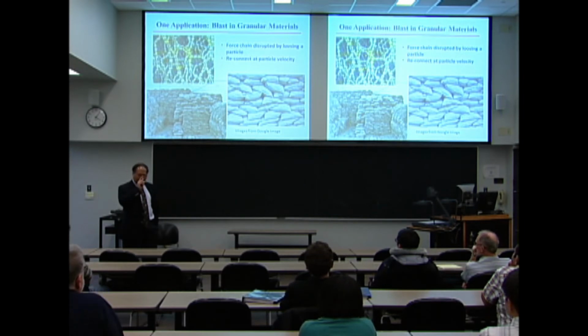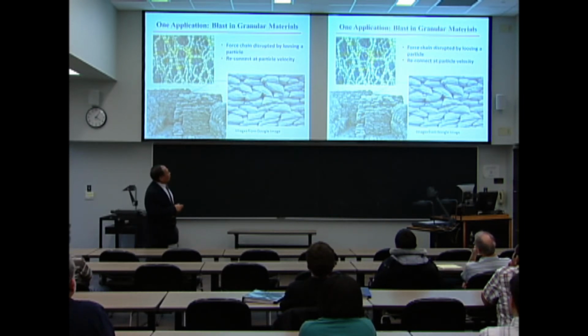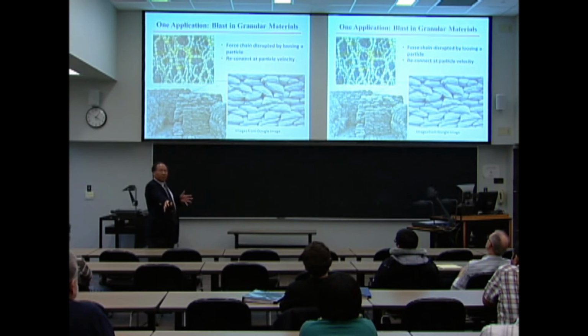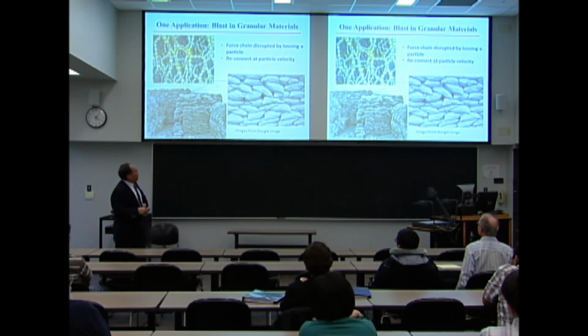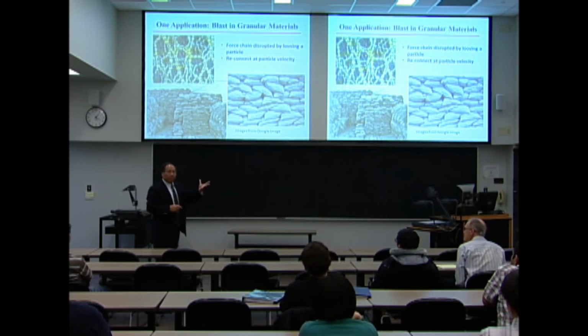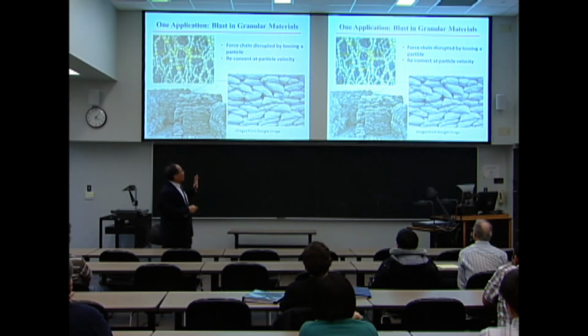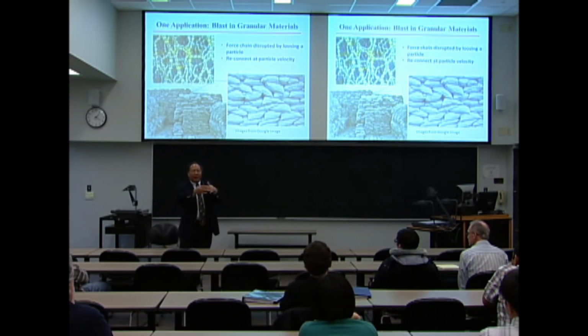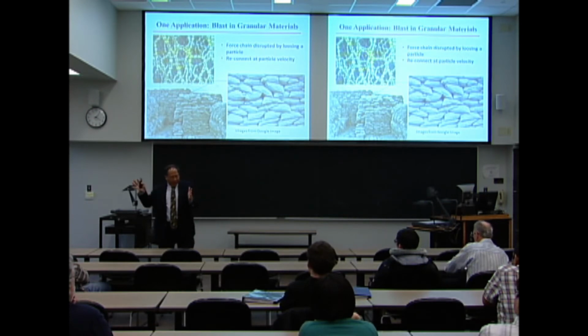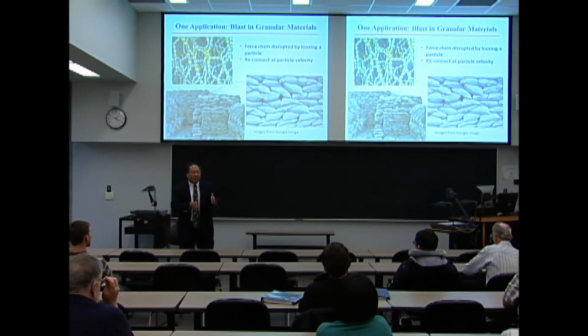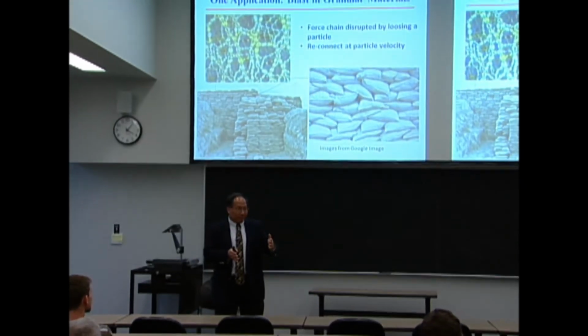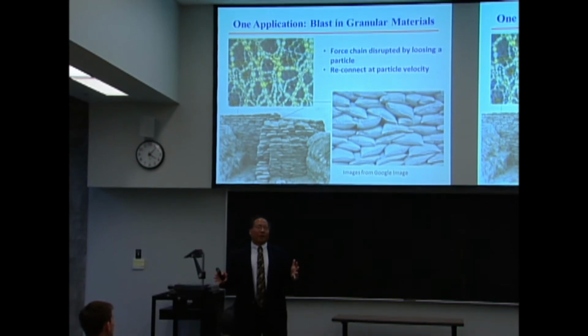If you think about how each grain fails, in the granular materials, load transmits through the granular material through specific chains of loading. Some of the grains can never get loaded. They always pick the strongest resistance to go through. So the experiments show that if one grain is going to fail, it will explode. It will disappear. So you're going to miss one link in one of the chains. Then it takes time for the chain to readjust, find the neighboring load to pass. That means the very high, strong shock can only propagate inside the sandbags near particle wave speed, near particle velocity, never at the shock wave velocity. So that's how sandbags isolate shocks.